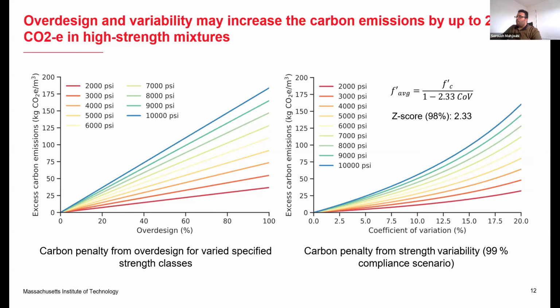And on the right-hand side, we considered 99% compliance with a z-score of 98%. And we use the ACI formula to relate the strength variations to the overdesign here. And we found that, again, the coefficient of variation has a significant impact on the carbon emissions, and the relationship is non-linear. And for higher strength mixes, the impact is more significant, and it can induce carbon emissions of up to 200 kilograms per cubic meter for high strength mixes.